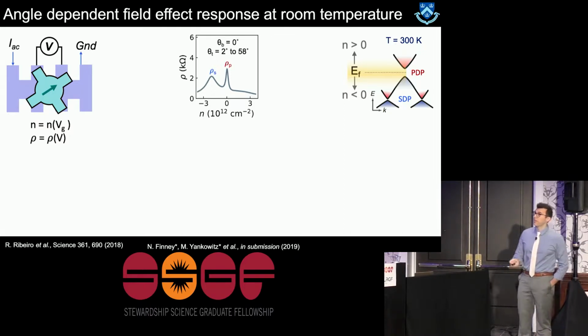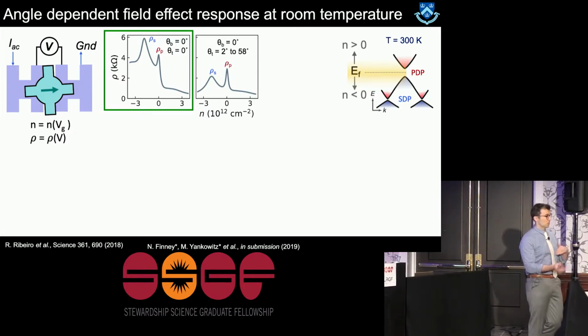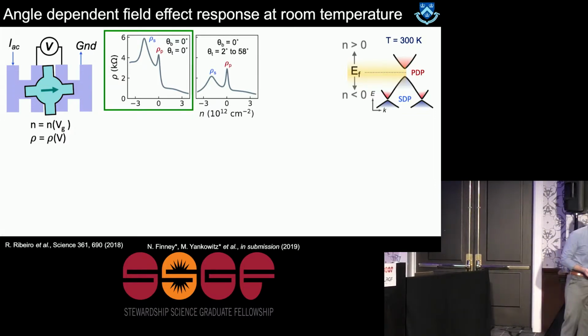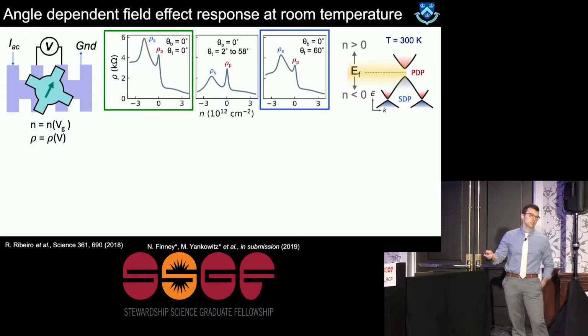channel. OK, now I take my AFM and I rotate it until I see some significant change in the sweep. So I'm labeling this 0 degrees, I see some maximum interaction. This is sort of a tentative label. And then if I rotate to 60 degrees, I see a slightly different peak, it's similar, but basically it's a suppressed enhancement. So at 0 degrees, I see this enhancement of the peaks, and then a suppressed enhancement at 60 degrees.